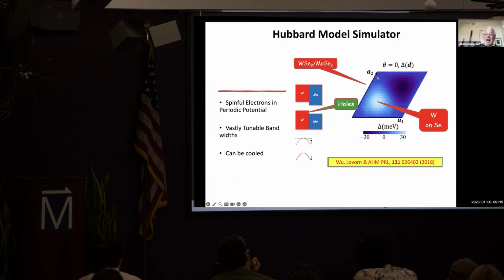And that's why, so this is the single electron Hamiltonian, it's just a periodic potential for spinful electrons. That produces bands. Those bands can be narrow, as I tried to say. And once you populate those bands with electrons or holes, you have to include the interactions between the electrons and holes. In particular, if you want to put more than one hole in the same moiré unit cell, there's a big energy cost for that. And that's the Hubbard U. It turns out that energy scale is typically 50, 100 meV, let's say. Okay? Anything else?